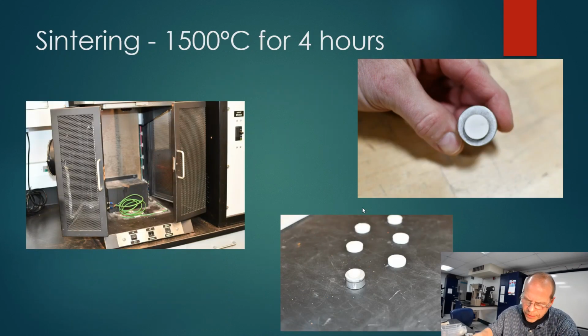So for both processes, powder mixing as well as the liquid infiltration, one of the final steps is a higher temperature sintering. And again, sintering, heating at high temperatures, we're going to take these discs and stick them in this oven, which is up in the ERC, and heat them at 1500 degrees C for 4 hours. Again, you might remember those pictures I showed you at the beginning where I was telling you I wish my samples looked like this.